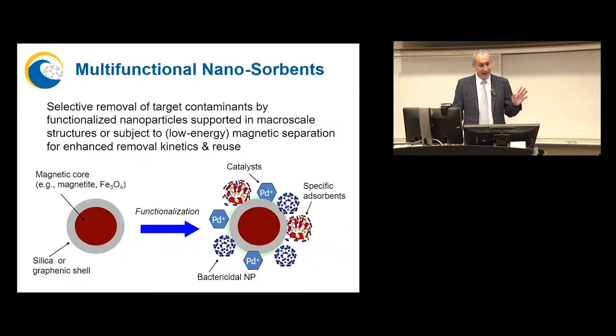Anyways, by the way, these superparamagnetic nanoparticles are excellent absorbents. Particularly of arsenic. We used them in Guanajuato. We had a project where one of the wells had a lot of arsenic. It's a mining area like here. Of course, they had sand filters that were doing a good job removing suspended solids and bacteria, but not arsenic. And we coated the sand with 5% by weight, and it worked really well for a while. In that particular location, there was too much silica, which interferes and is preferentially absorbed. So we only got like 2,000 bed volumes, but in other places you can get 10, 15,000 bed volumes.